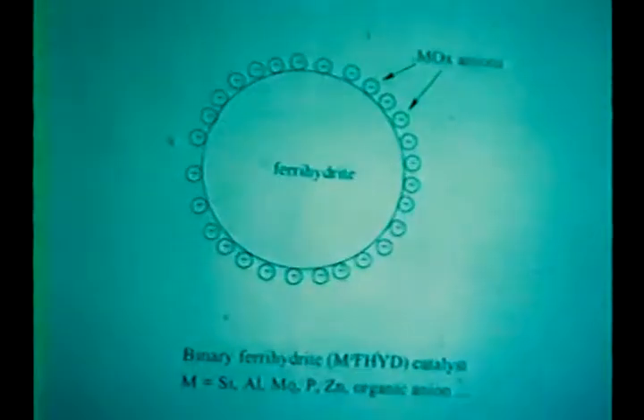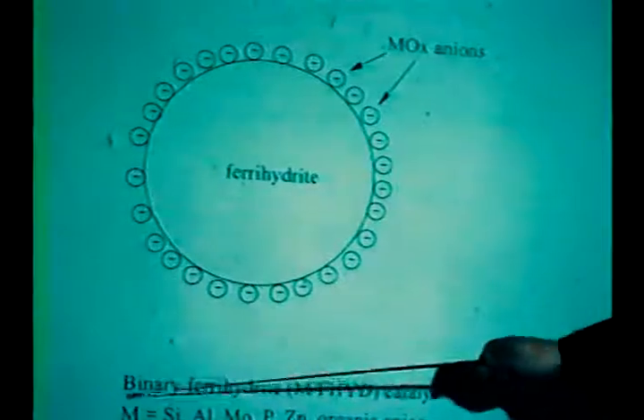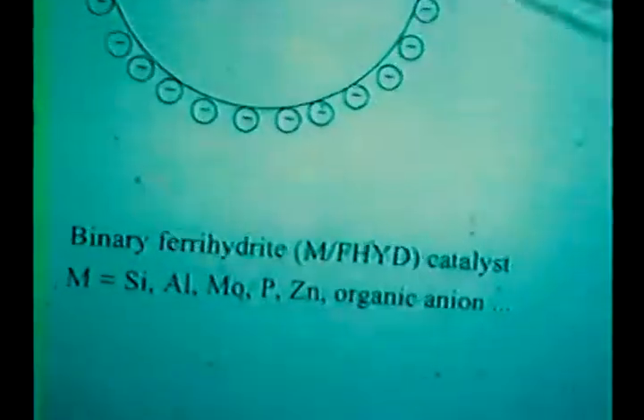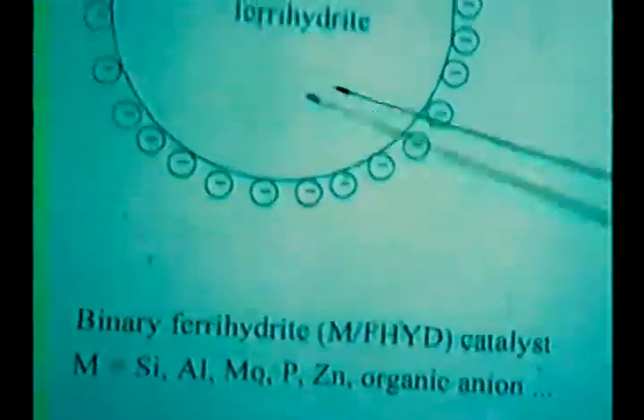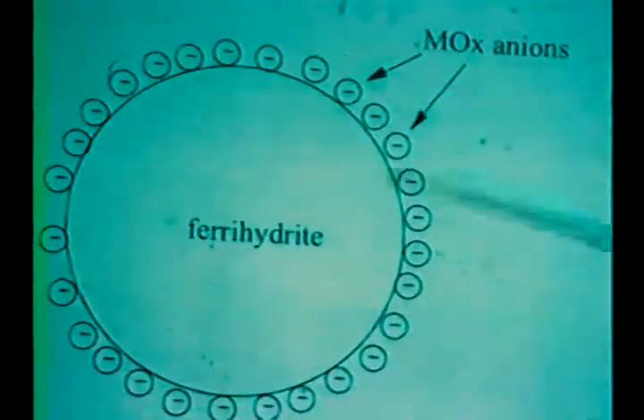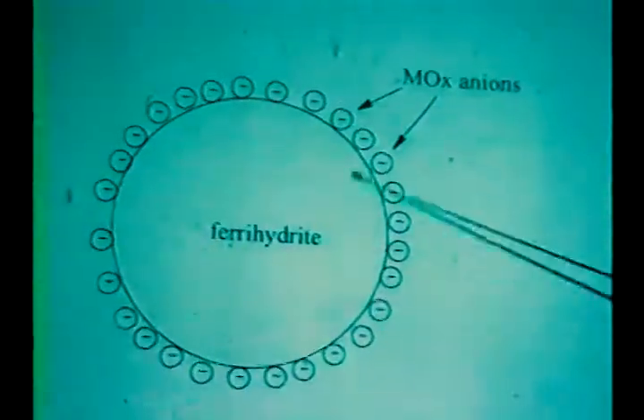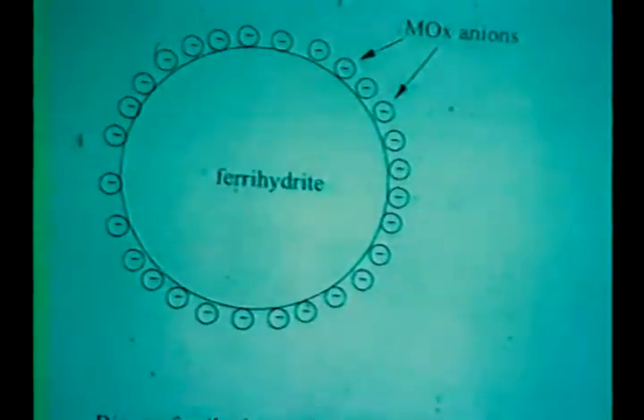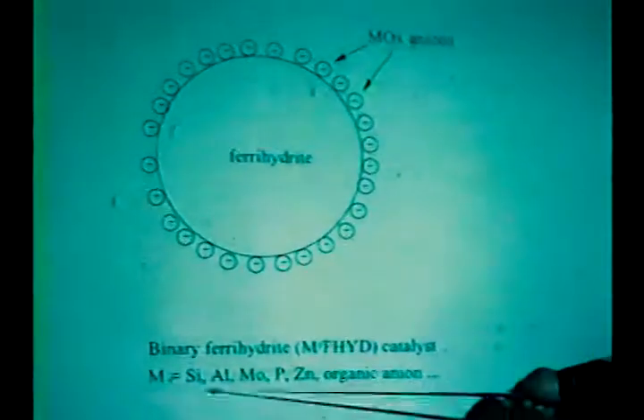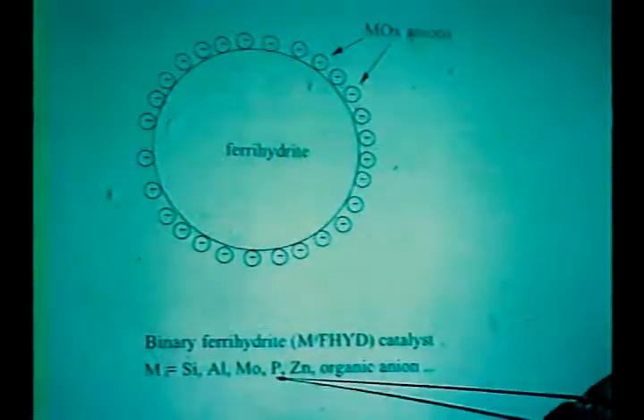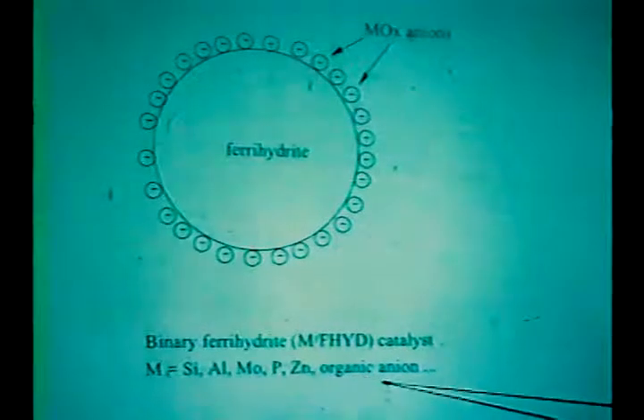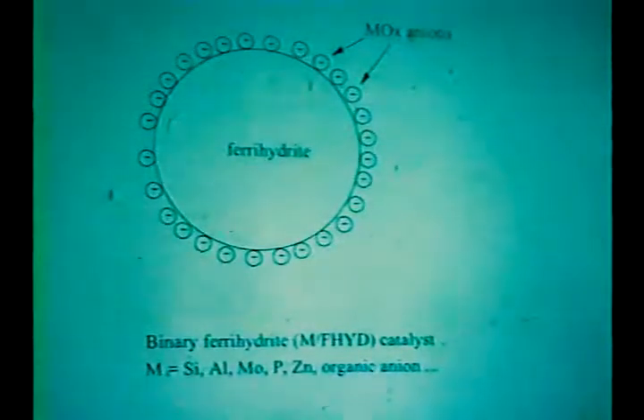So we try to add some impurity to the precipitation solution. What we got is we call binary ferrihydrite. The bulk part is ferrihydrite, but the surface is absorbed with impurity ions. We successfully put silica, alumina, moly, phosphorus, zinc, and organic ions at the surface.